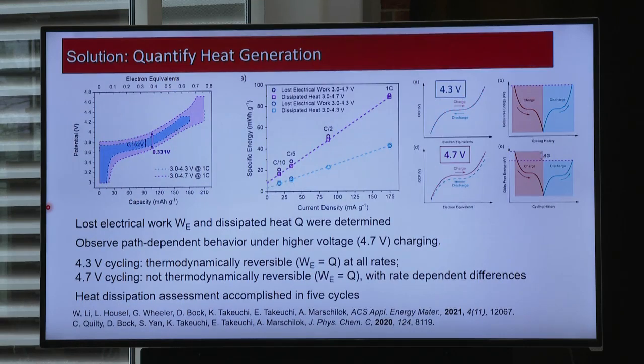We looked at what's called the voltage hysteresis and the back and forth voltage profiles, meaning if you charge and discharge, and they follow the exact same voltage profile, it gives you a better sense that things are reversible. And at 4.3 volts, that's the case. At 4.7 volts, that is no longer the case. The trajectory for charge and discharge of the voltage profile is not the same.